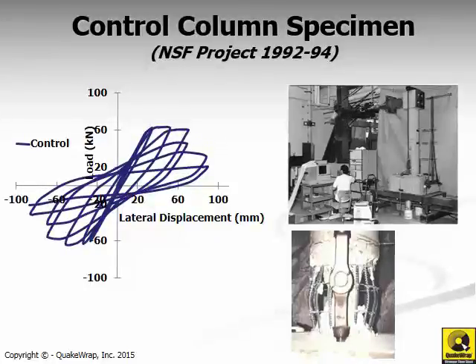There are rods that are running along the height of the column and the jacks below the frame. With those rods, we applied a load of about 100,000 pounds to the column, an axial load. And then that load was held constant while the actuator would push and pull the top of the column in a reverse cyclic motion. The result of that hysteretic behavior of the column is shown on the left graph. And as you can see, these columns, which were modeled in fact after the older columns with fairly large spacing between the ties, after a couple of cycles of load reversals, you notice that the load carrying capacity of the column is significantly reduced, and as we push the column further, the column cannot resist so much load. This behavior is obviously not desirable and is one that has to be enhanced.